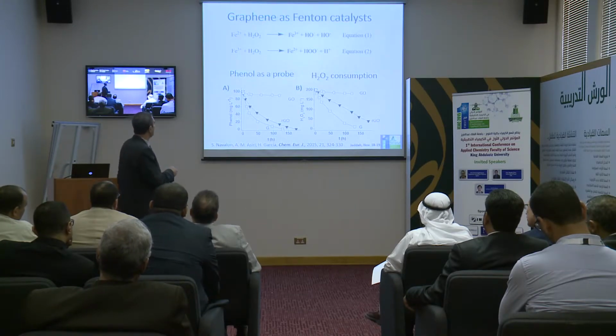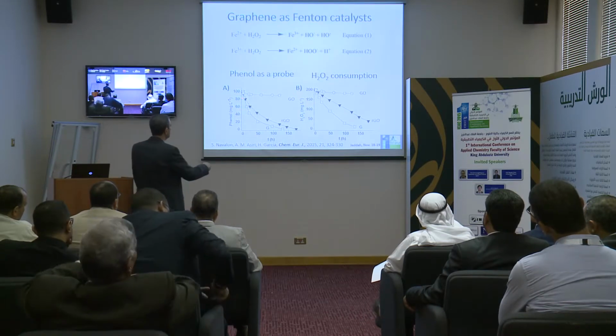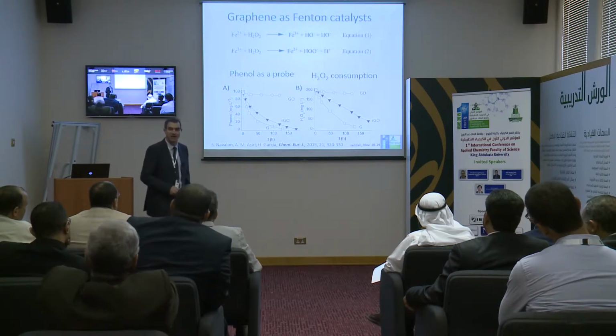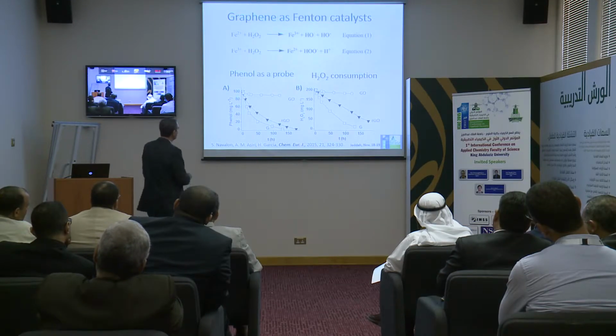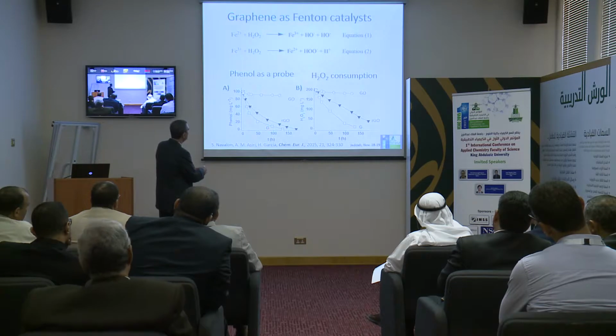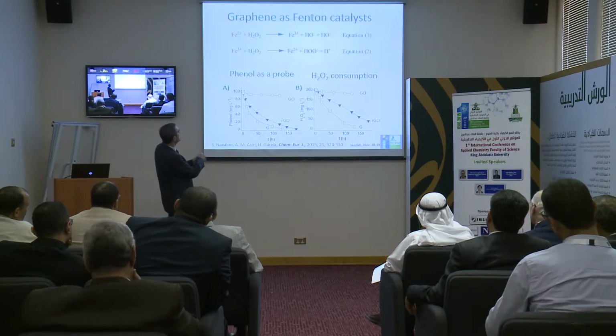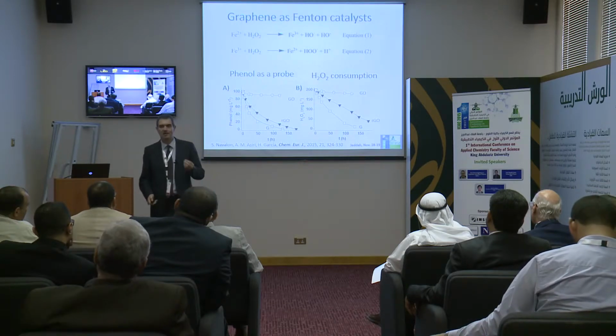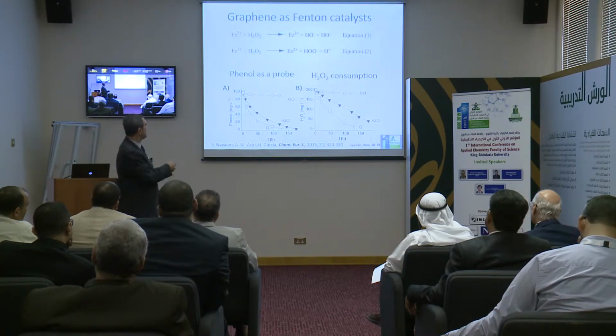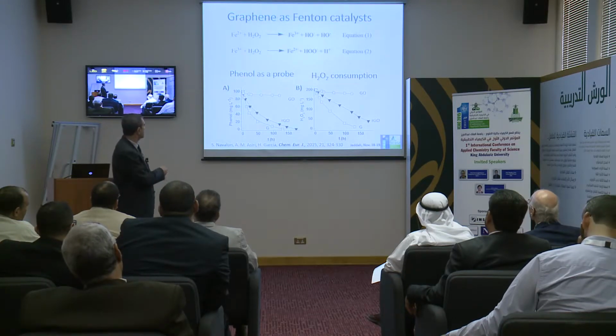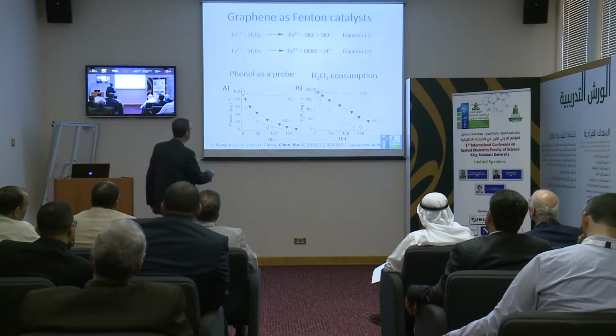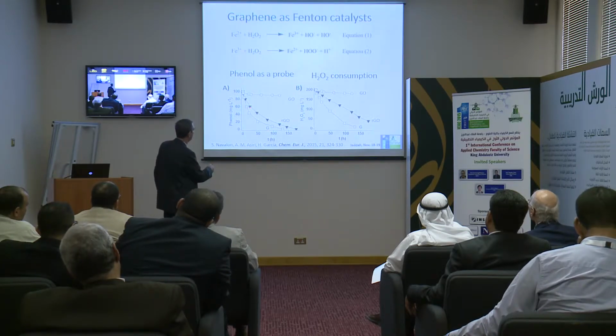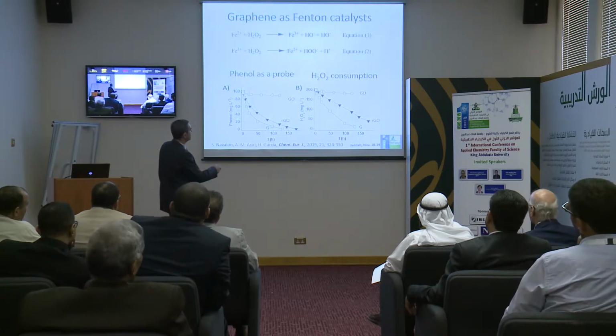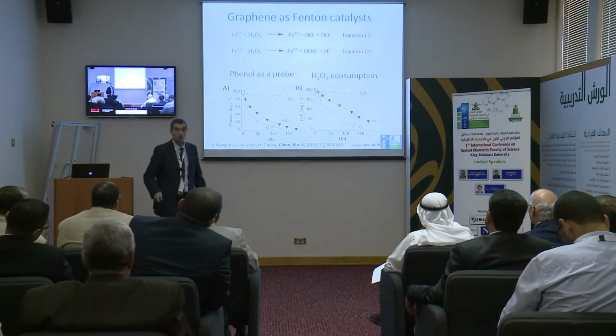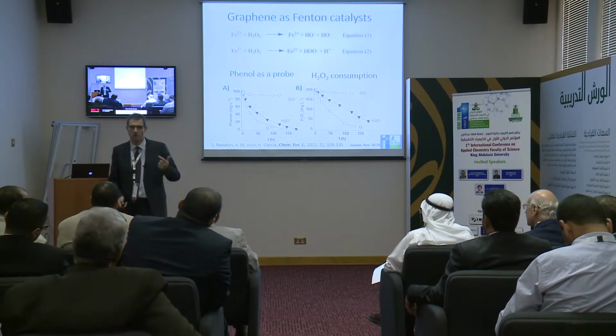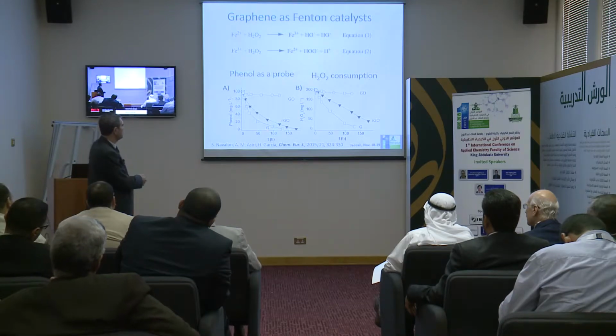It's possible to develop a graphene that is able to do this reaction, and these are the temporal profiles of the reaction showing that our graphene is very efficient for the Fenton chemistry. So this is reduced graphene oxide, and this is one graphene, and we are following two plots. One plot is phenol. Phenol is the IUPAC recommended molecular probe to test the Fenton. Over the time, using reduced graphene oxide or our graphene, we can decompose phenol, and this is another graphene oxide in which the activity is lower. So there are some graphenes that are very good, other graphenes that are not that good. It depends on the composition of the graphene.